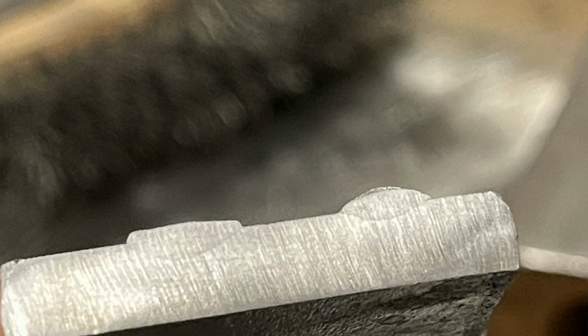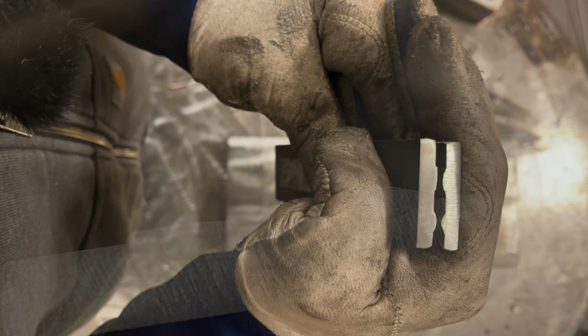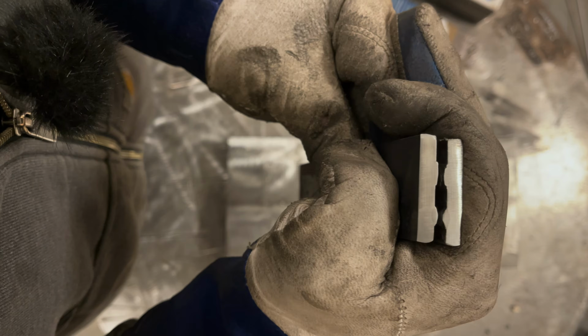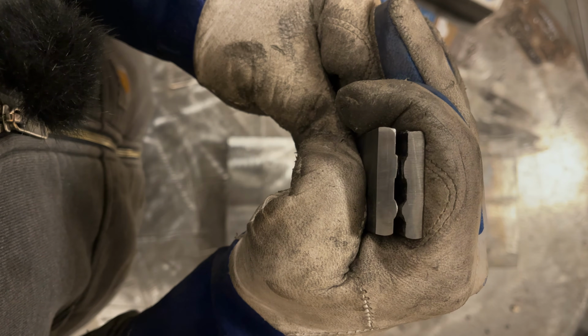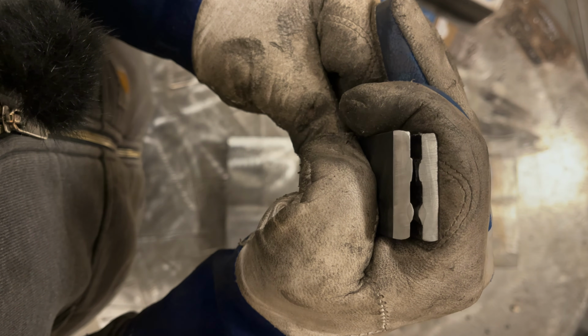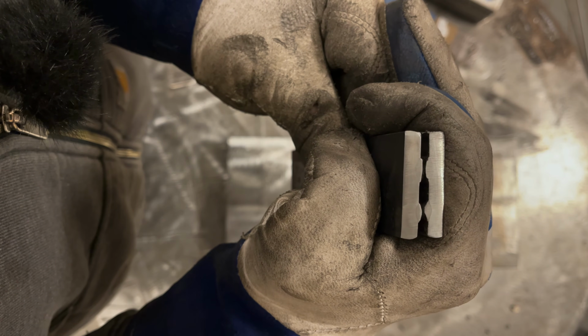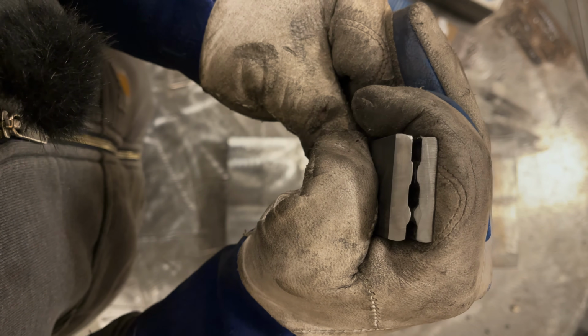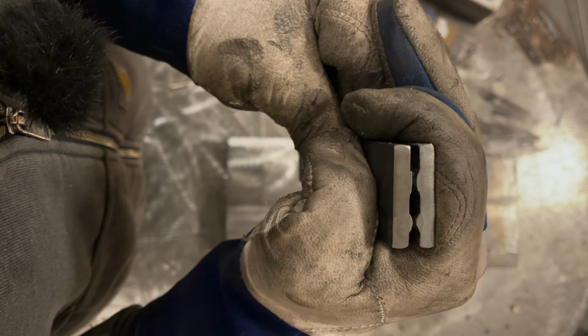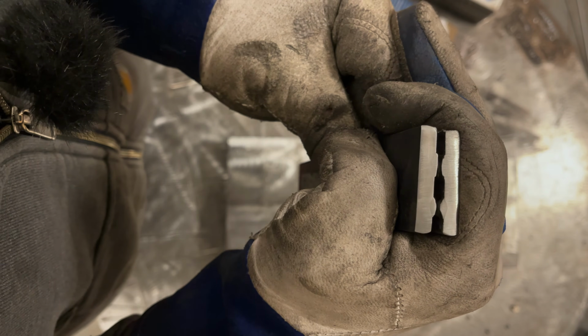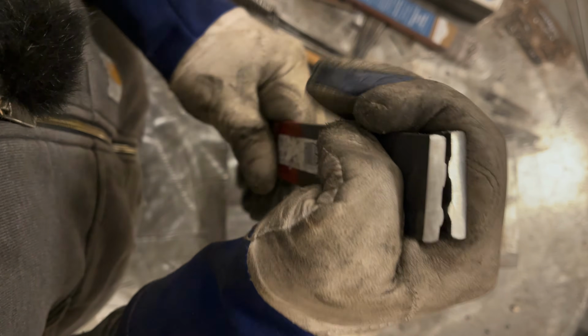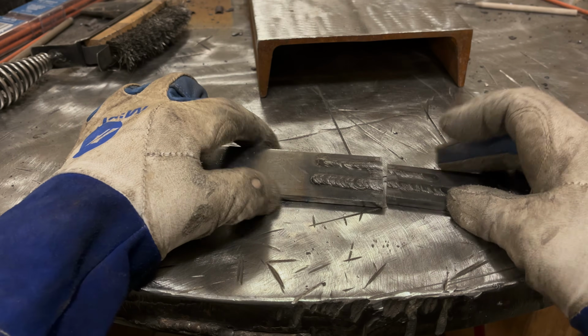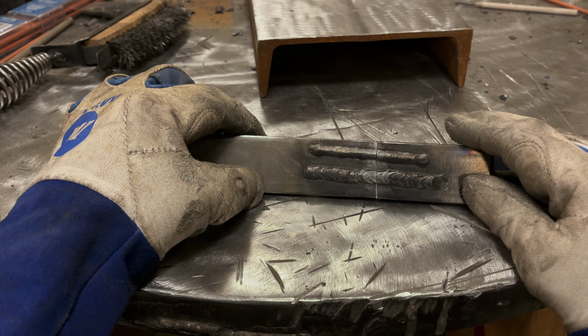Now on my welder, I welded both of these rods with the same arc force setting of 30%, just different amperages. And you can see despite having more amperage, the 7018 just did not penetrate more. Had I run that 6010 at even more amperage, it would have likely gone even deeper for penetration. And this kind of reinforces the differences between the rods themselves. All right, as you saw in the cut and etch, there are differences here.